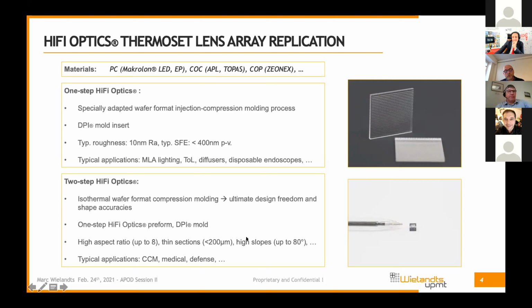And this allows us to overcome the limitations of classical injection molding. So the higher aspect ratios, up to 8 that we have done, thin sections below 200 microns, very high slopes. It's a slow process, but because of our technology for the mastering, we do many lenses at the same time. So we produce these in wafers where there are hundreds of lenses.